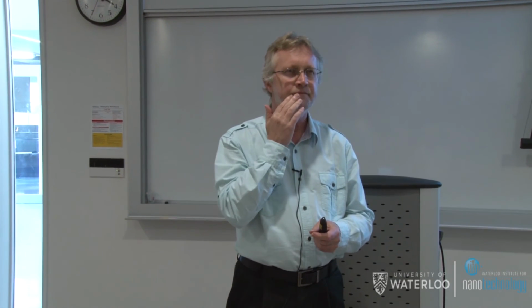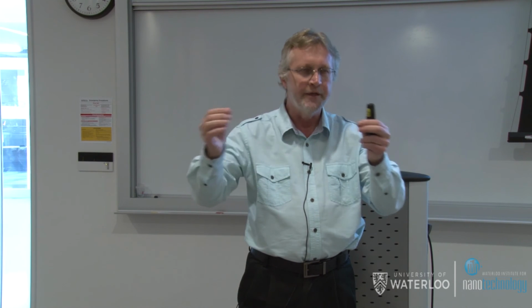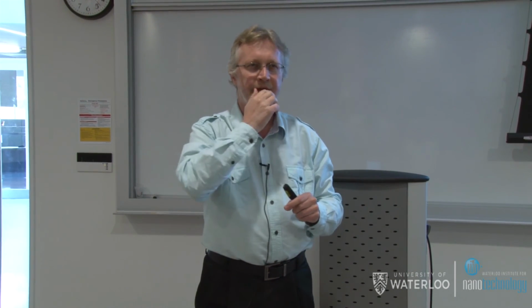When you draw these fibers out of the molten state, you probably can't do it in the liquid nitrogen, right? No. These fibers, what you are seeing is at like 180 degrees, just below the isotropic fluid state, just a few degrees below that. You just have 2 pins and a drop of that, and then when it goes to the smectic phase, you separate them, and they make a necking, and it has a meniscus, and then it becomes a completely constant thickness until you have no material left. And these are quantized, kind of. One molecule wants to make a 1.57 micron diameter. The other one wants to make a 3.2 micron diameter.